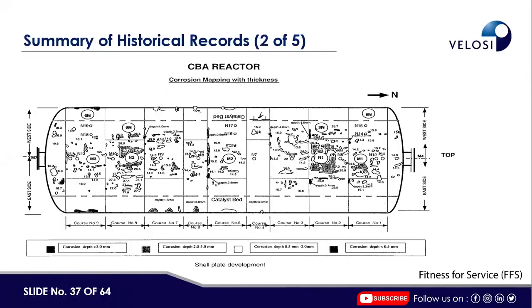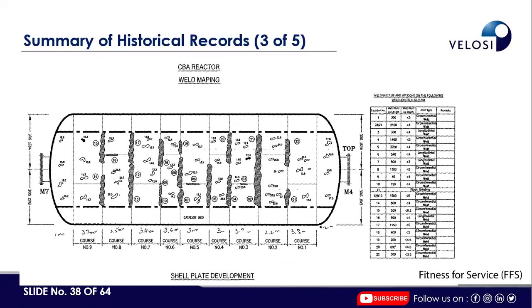So this is the location of the spread of the defects on the GA of the vessel. If you see, the defects are more near to nozzle number 1 and nozzle number 2, and you will see the cause of these defects, like flashing of the product when it is coming inside the reactor, could be causing a low dew point for the water content of the acid gas, and that water content might be causing some heavy corrosion. The other locations of the defects are near the weld seams. These are the seams of the welds of the various courses, and these are some locations there.